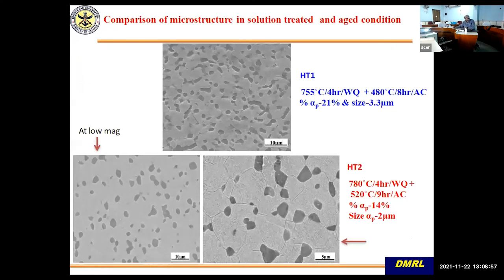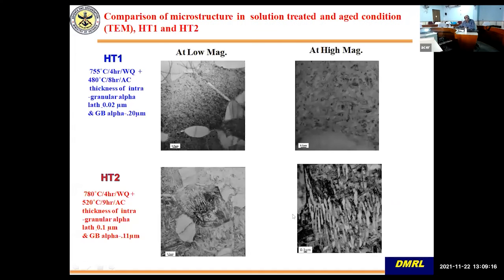Here I am showing you the microstructure. First heat treatment, you can see the higher amount of primary alpha, and this is very fine secondary alpha. In the second, this heat treatment has got lower volume fraction of primary alpha, the dark colored, and coarser secondary alpha. The fine secondary alpha is what gives you strength, and the coarser one improves the fracture toughness.